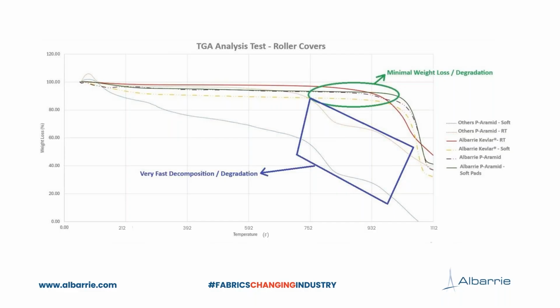Then the lines marked Albarrie Kevlar and para-aramids, both the soft and the resin treated, also show excellent performance with minimal weight loss up to 1076 degrees Fahrenheit and gradual degradation thereafter. These materials are well suited for mid-temperature zones, providing a reliable balance of heat resistance and durability.